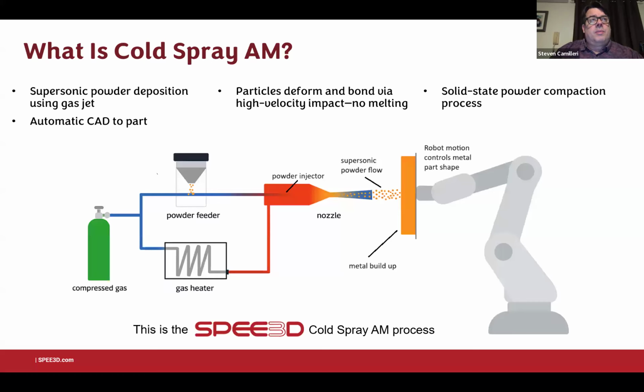So we've really had to work very hard to make sure the nozzle itself gets minimally affected by the cold spray process. So you want it to be as reliable as possible. You want to minimize erosion. You want to minimize clogging, and doing that cheaply and ending up with a nozzle that's commercially available and reliable is a very difficult engineering task. So we've put a lot of time into that, which I'd guess we probably have other cold spray vendors here. I guess most people don't think about that very much, but that's been a dominating effect for us.